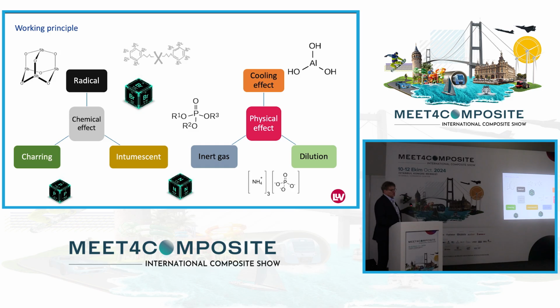Now I want to talk a little bit about the working principles of flame retardants. You have chemical and you have physical effects. If you have chemical effects, you must make a difference between three different mechanisms. One is radical formation, which avoids the oxidization of your material. One is a charring effect, which builds up a layer of carbon on your part and so separates the material from the fire. And then you have the intumescence effect, a strong, hard word, where you have a kind of foam formation, which also makes a separation between fire and material.